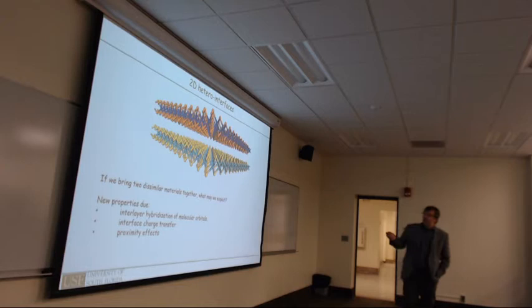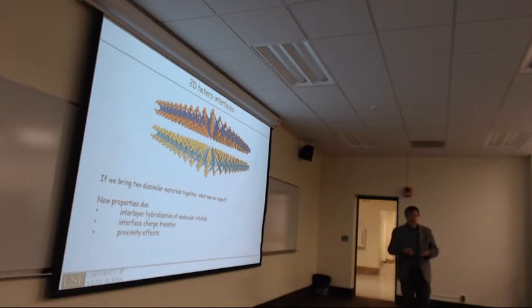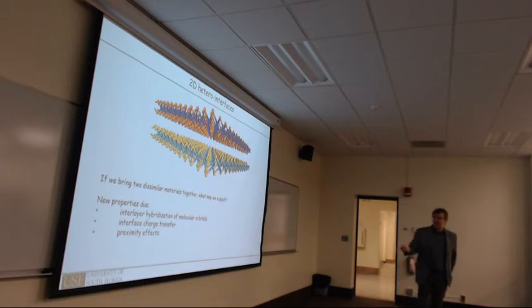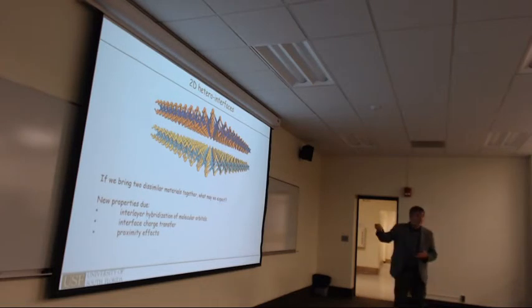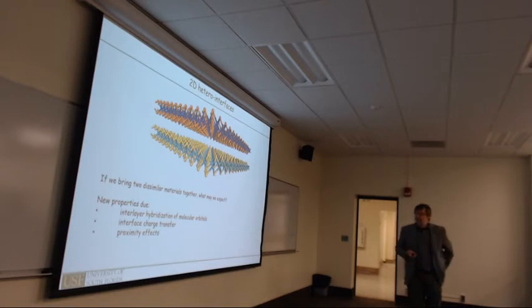So if you combine one transition metal dichalcogenide with another, we expect that there are new properties due to interlayer hybridization, like let's say the tellurium-tellurium hybridization of the molecular orbitals. Certainly you may get interface charge transfer from one layer to another, and then there could be other proximity effects that affect the properties, like the dielectric environment of one material in the presence of the other.